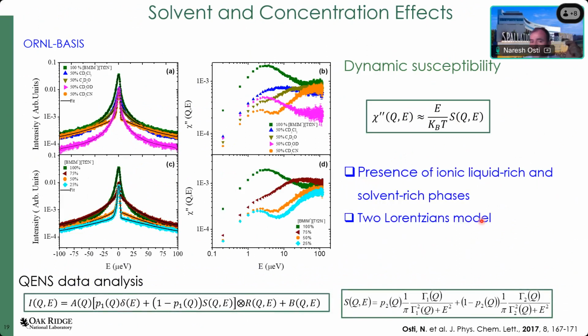Now we move to the quasi-elastic neutron scattering experiment. What we did here, I would like to remind you, as I said before, is that the beauty of this technique is that you can selectively pick the information that you get from one component versus another component. Here we are using the ionic liquid. The cation has hydrogen, and our solvent is all deuterated solvent. That means whatever signal we get is only from the ionic liquid, not from the solvent.